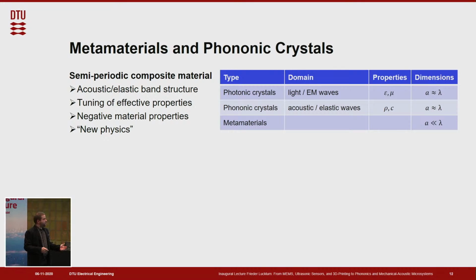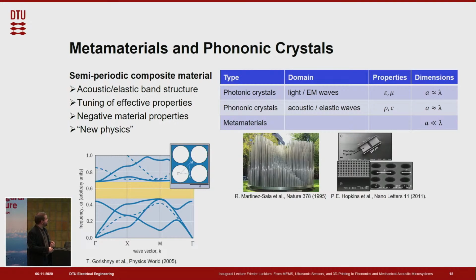And the way to achieve that is, as before, by the microstructure, by achieving a certain composite behavior, creating a composite material. And this composite material can be periodic, so regularly arranged, semi-periodic. It can also be not periodic at all. But when we talk about phononic crystals, we are talking about a periodic arrangement of this microstructure. An example is shown here. This is an art sculpture which is in the city of Madrid, and it's actually the first demonstration of a phononic crystal in the real world.